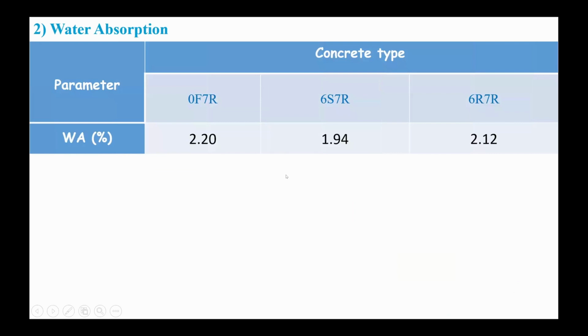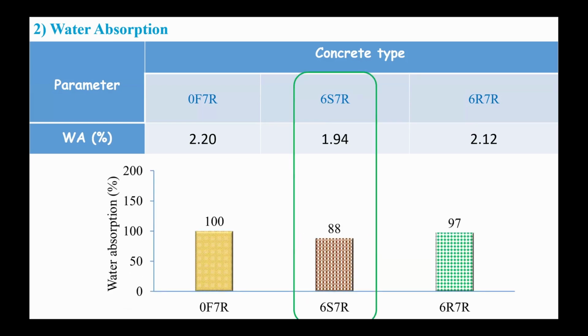Water absorption: there was somewhat of a decrease in water absorption as compared to the plain concrete. You can see here that the maximum was for the industrial steel fiber for the same dosage of the fibers. But there was also a minimal 3% decrease in water absorption at 0.6% of the recycled steel fibers as compared to the plain concrete.